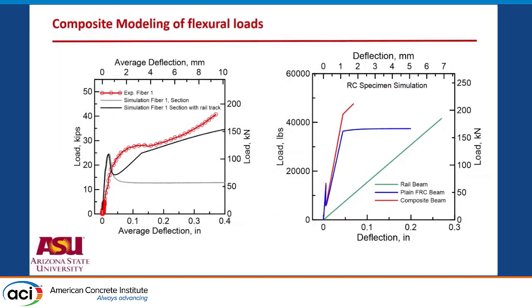Again, this is another set of comparisons. What is the difference between the reinforced concrete and the fiber reinforced concrete? Mind you, we're only looking at a service level here. Everything we're getting in the fiber domain is additional ductility, where you can go much, much higher. But in the reinforced concrete, your deformation before yielding is somewhere about 0.15, not less than 0.1 inch.